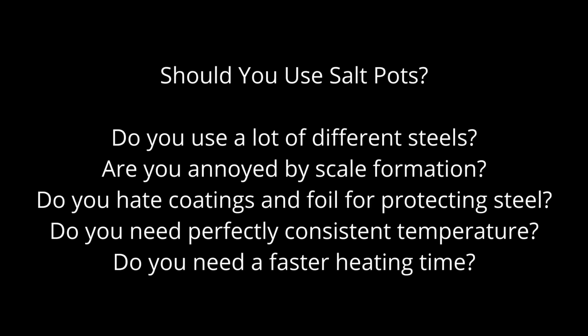But if you're outside of this range of the neutral salt B, 1300 to 1700, like you need to heat treat a stainless or a high-speed steel from a higher temperature, you need to get a different salt. And so you would need multiple pots with different salt types in them to be able to work in the right range. And that is a little bit more than I want to handle. But I am doing experiments on lots of different steels. I am not a knife maker, and so my needs are a little bit different.